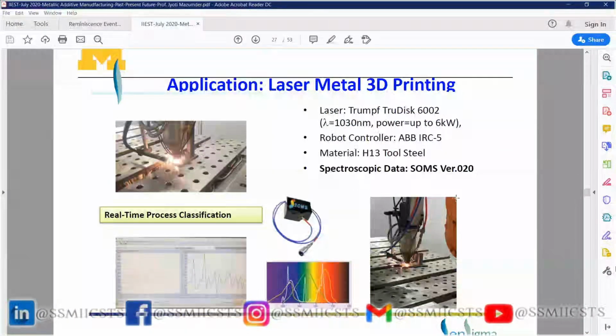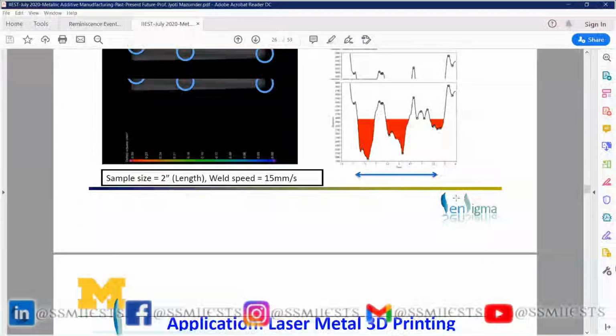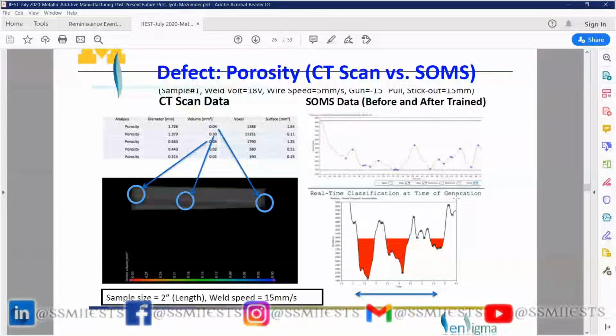What we find, to our own surprise, is that even if the defect is subsurface, we can pick that up too. What you see is the software we developed: whenever there is an anomaly in the plasma, we can put this red line during the defect. So not only the surface defect, we can also predict the subsurface defects in the material. And this is just to give you an example. This is the process you're depositing, and you can see online all the spectra, and we can analyze that. In fact, I just filed a patent last week.